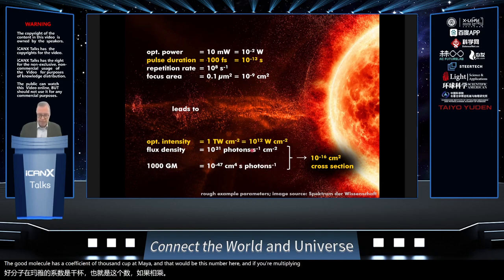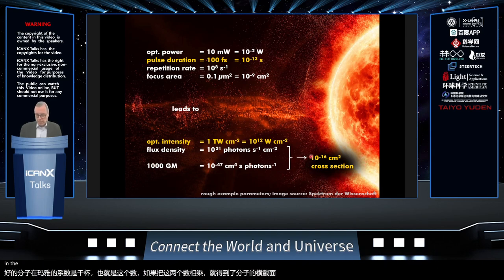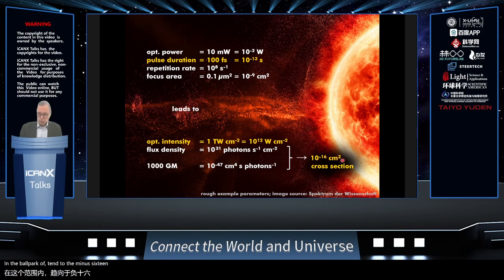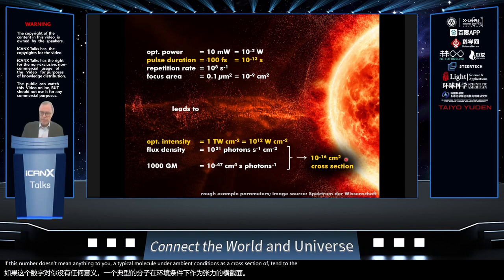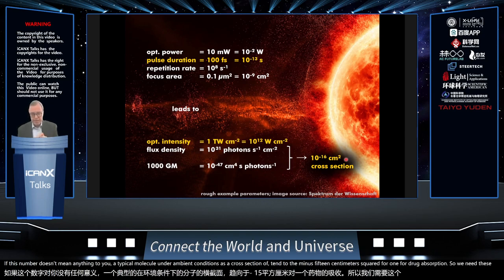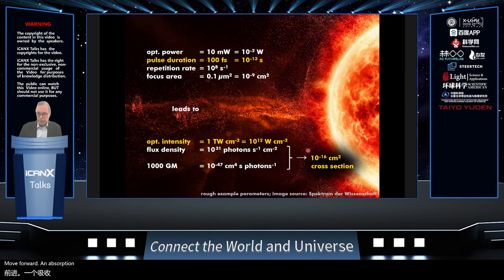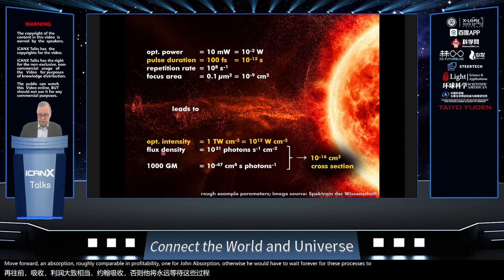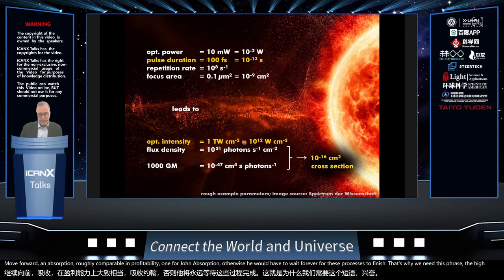And if you multiply these two numbers, then you get a cross-section of the molecule in the ballpark of 10 to the minus 16 centimeters squared. If this number doesn't mean anything to you, a typical molecule under ambient conditions has a cross-section of 10 to the minus 15 centimeters squared for one photon absorption. So we need these crazy high intensities for two photon absorption to make it roughly comparable in probability to one photon absorption. Otherwise, you would have to wait forever for these processes to finish. That's why we need these crazy high intensities.